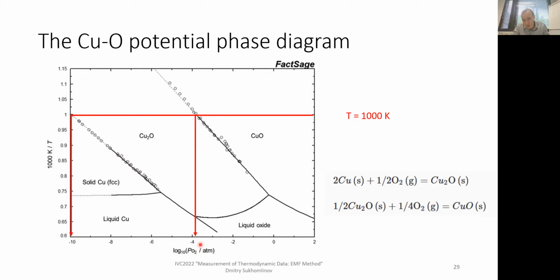Or in other words, if we have copper, we heat it up to 1000 K, and in the gas phase we have this oxygen partial pressure, then, let's say if it is 10 to minus 2, eventually it will oxidize to CuO. If it's 10 to minus 6, then it's Cu2O, and so on. And to keep it metallic, it should be less than 10 to minus 10. Let's remember these numbers. So temperature is 1000 K, metallic copper and Cu2O 10 to minus 10, Cu2O and CuO around 10 to minus 4.